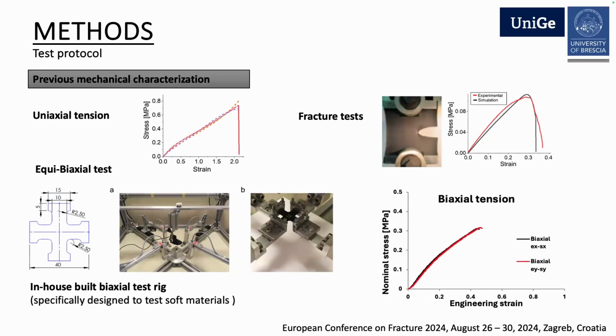And considering specimens that were printed flat onto the printing bed, we carried out this test mainly to verify whether there was some kind of anisotropy, but at least in the planar direction, apparently the material is isotropic.